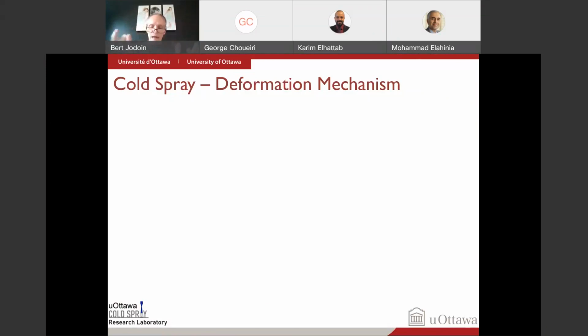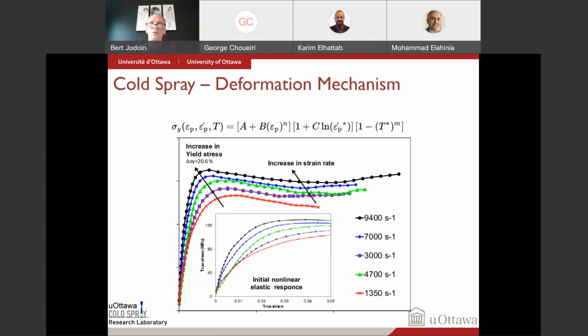How does this work? What happens to a particle when it impacts your substrate? Well, you know that your flow stress depends on the strain rate and the temperature. So you've seen this in your material courses where you have the work hardening term, the strain rate term, and the thermal softening term. So if we look at the stress strain curve, let's look at the red one here. Well, you know that you're going to get work hardening. So as you deform, it becomes more and more difficult. You need to push or pull more and more to deform even more.